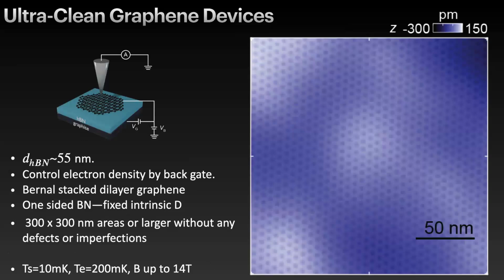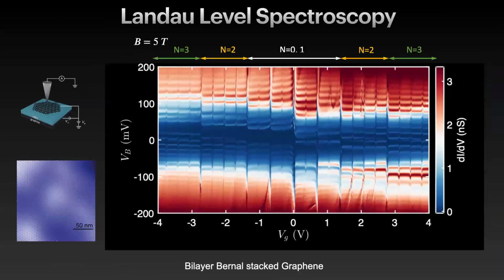So here is a bilayer graphene device. It's not twisted, but the boron nitride moiré is still there. And we cool it down and apply a large magnetic field. I won't go into the details of the system, but n equals 0 and 1 are nearly degenerate in the system. And the first advance that I want to point out here is spectroscopy. These lines are all Landau levels, and what you notice is that the Landau levels are just flat lines, like they should be.